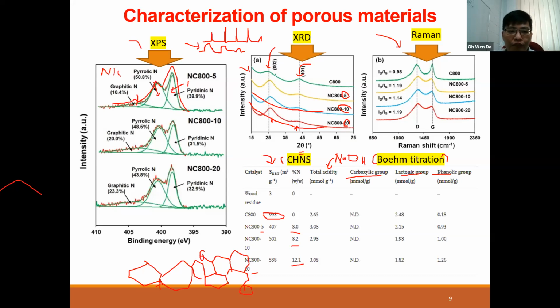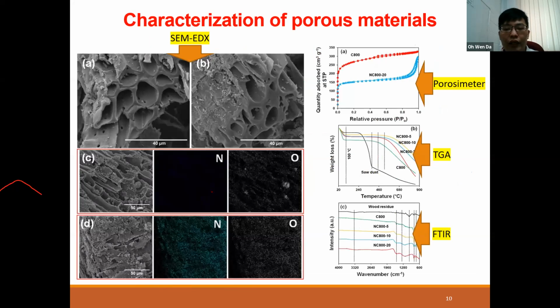So before adsorption, you have these 3 groups at 23, 43, and 32%. After adsorption, if your pyrrolic nitrogen group disappears, then you can match all these things together. You can correlate this, and then you can deduce that the pyrrolic nitrogen is the active site for your adsorption process. Other things, again, just to quickly go through this, SEM, look at the pores. You can see the pores, right?